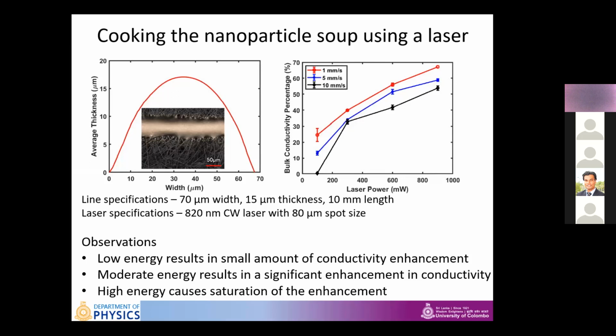So we connect our laser to a moving head and translate it over the trace at different speeds and different laser powers. The graph on the right-hand side shows you what happened to the conductivity of such traces after we cook them using our laser. Now here the x-axis of the graph is the laser power in milliwatt. Y-axis is the conductivity of the trace as a percentage of bulk. Now, 0% indicates non-conducting, 50% indicates half as conductive as the bulk, 100% means conductivity of bulk.